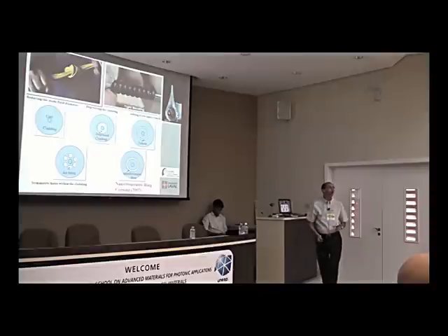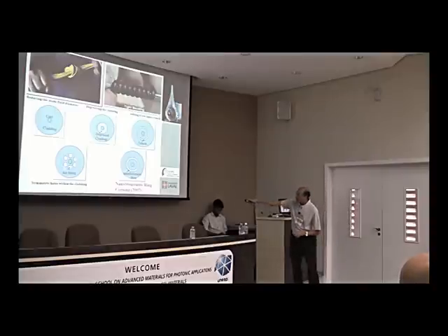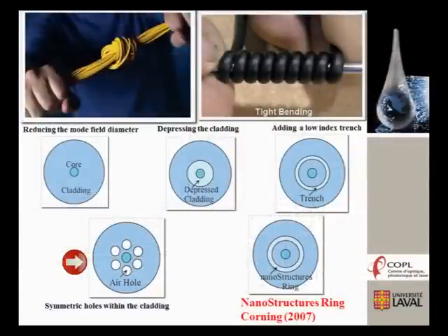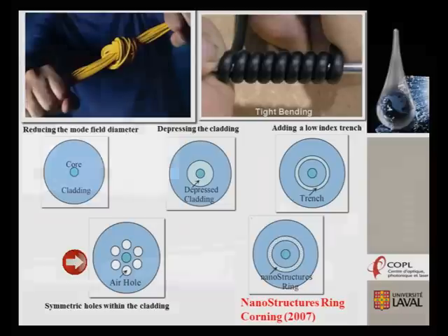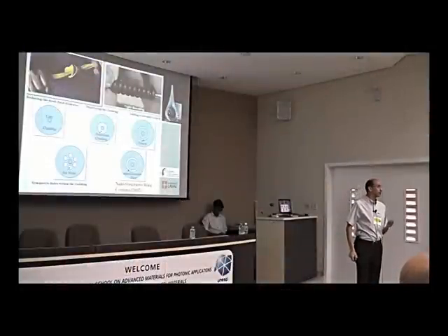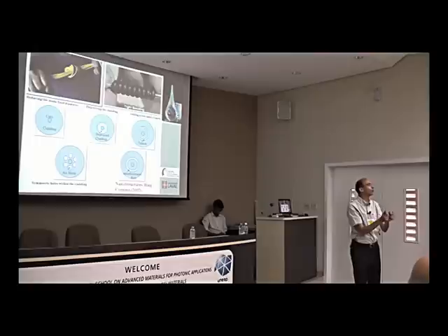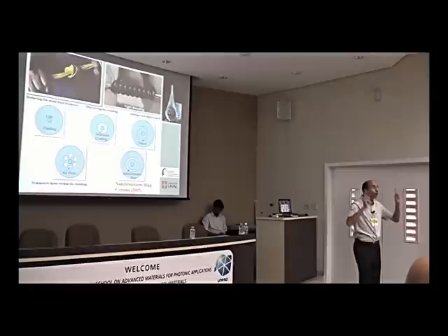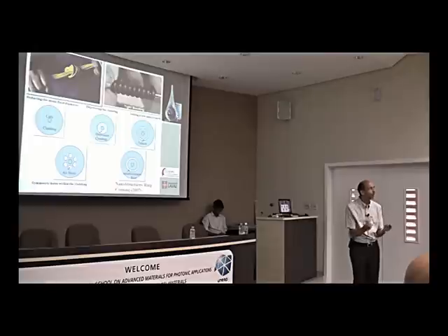Recently, again, Corning showed that yes, we will be able to do what we told, a fiber with the structure, what we call microstructure, with symmetric holes, and allow them to get a higher bending, or insensitive to bending, insensitive to bending. Do it in the way that you want. And this is something that opens the door mainly for the telecommunication application. We can get, using now this fiber, I can get this in my house, we can get this for other applications.